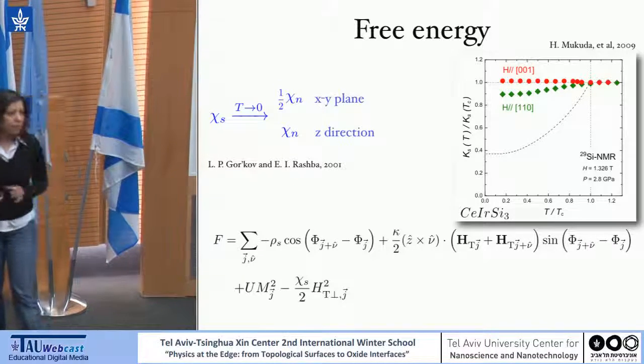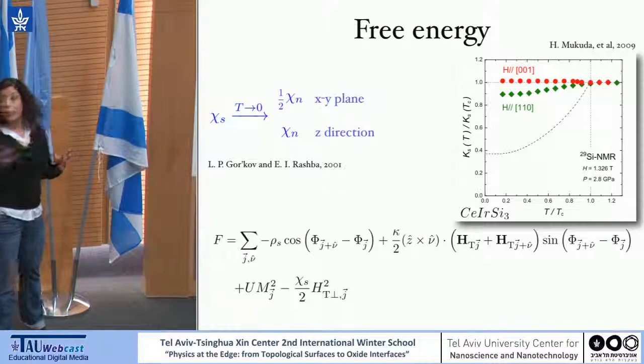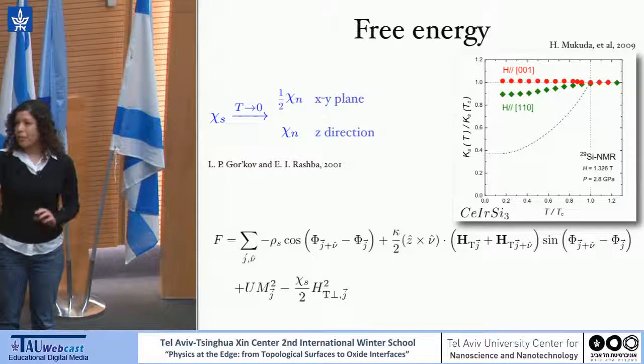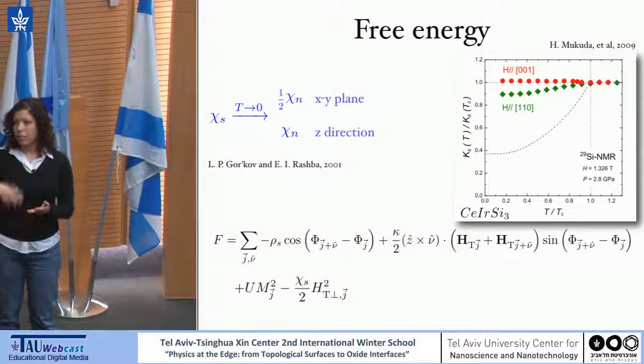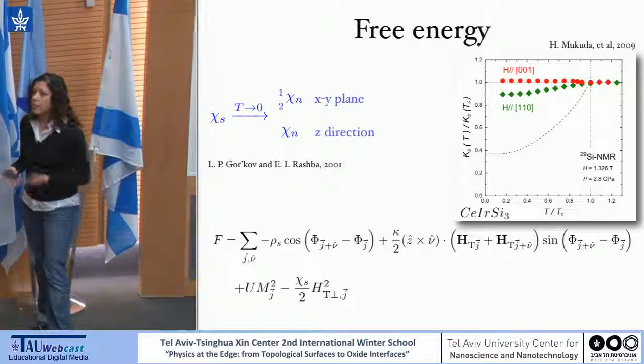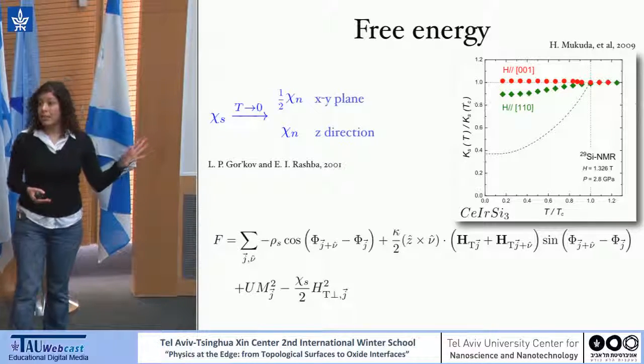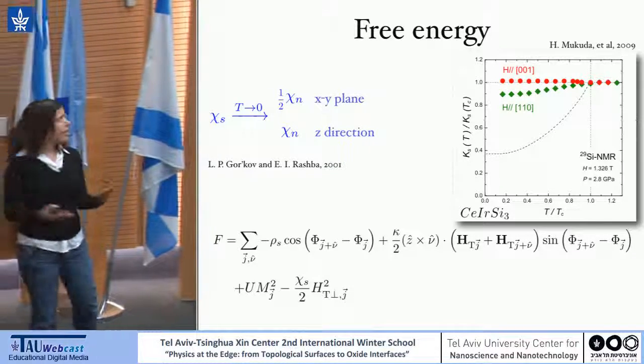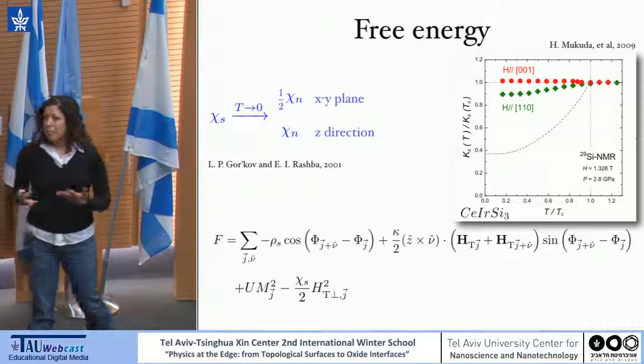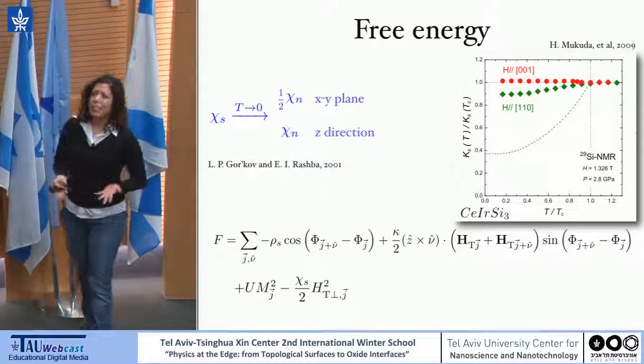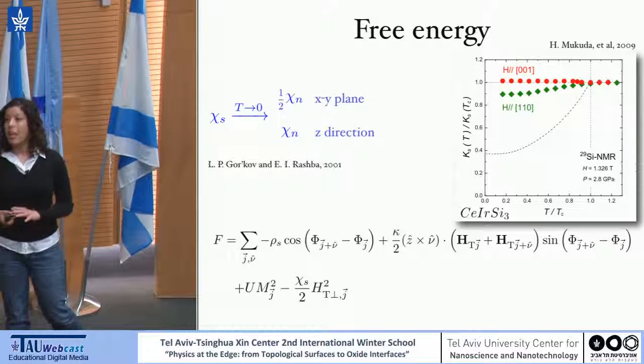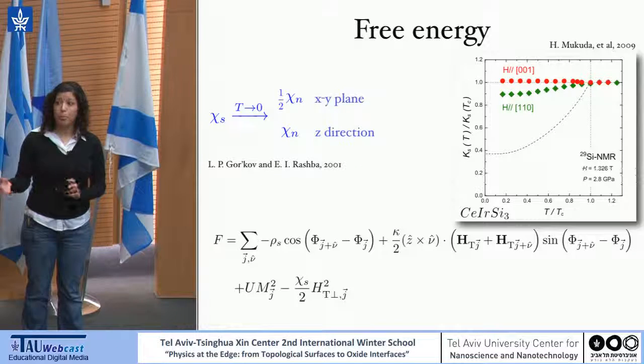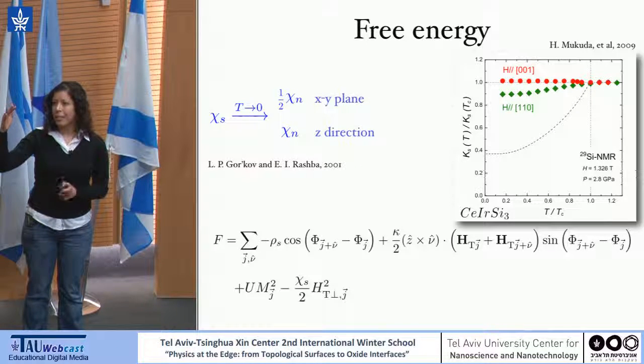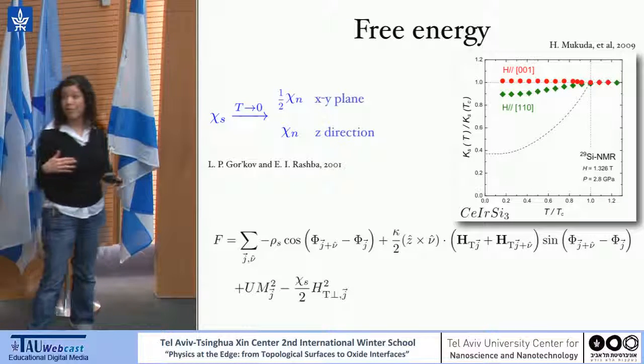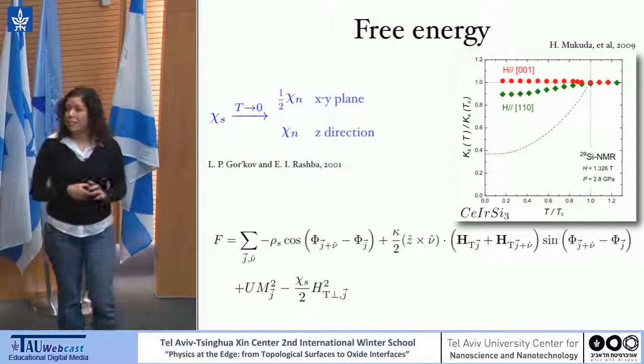They did. But in general, there are a few questions. Spin triplet superconductivity, even in the presence of spin-orbit coupling or not, is very sensitive to disorder, while here the spin singlet is completely immune to disorder. And at least for the LAO-STO, you would assume that there is enough disorder in the system that spin triplet is probably not very favorable. But also in the case of spin triplet superconductivity, TC should not go up. It's indeed more immune to magnetic fluctuations or any kind of fluctuation and to magnetic field, but it still should not increase TC.